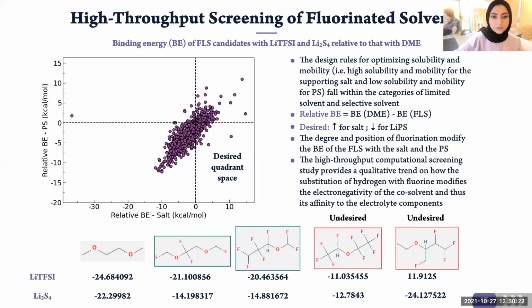We computed the binding energy of each fluorinated solvent with both the salt and the polysulfide with respect to that of DME, which is the conventional ether solvent that we are trying to replace in this project with the fluorinated solvent. So a high relative binding energy, according to this equation, means that we have a higher affinity towards a certain component compared to the conventional glyme solvent. So it is desired to have a high relative binding energy with the salt and a low relative binding energy with the polysulfide, which means that the lower quadrants here are preferred, and even like this the third quadrant here is more preferred over that one, from which we can select the fluorinated solvents of interest, because they have lower binding affinity towards the polysulfide, but usually higher towards the salt.